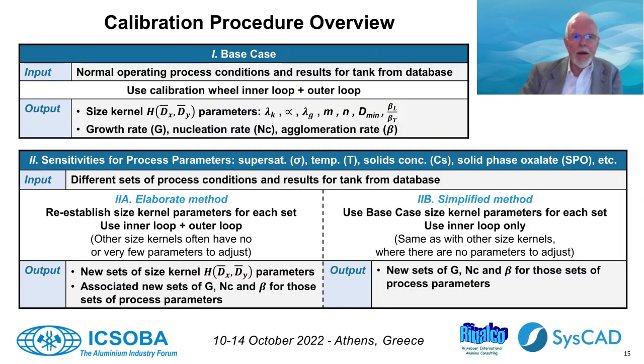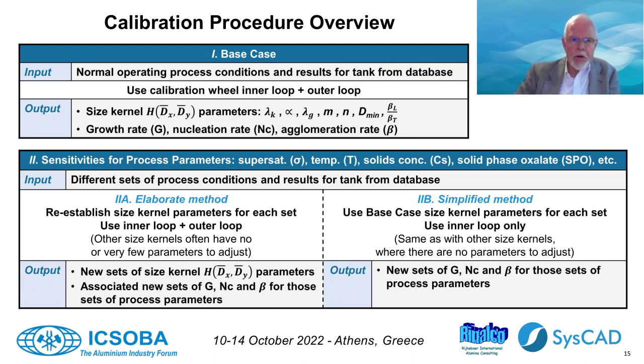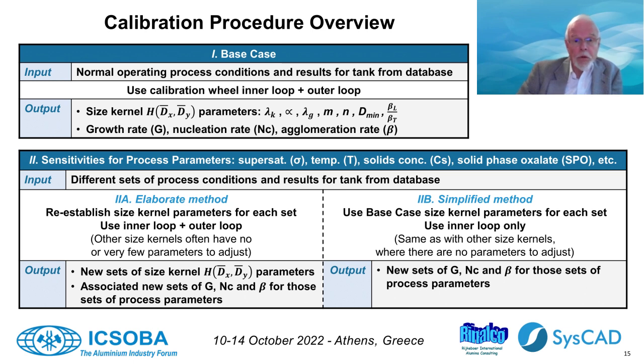The next step is to find out how growth rate, nucleation rate and agglomeration rate are correlated to such process variables as supersaturation, temperature, solids concentration, etc. The elaborate method uses inner loop as well as outer loop, thus the size kernel parameters are in principle subject to change as well. This is labor intensive and a bit far-fetched considering that other kernels don't even have such a set of kernel parameters to begin with. So for now, we will follow the simplified method and freeze the kernel parameters found in the base case for the particular precipitator or group of precipitators.